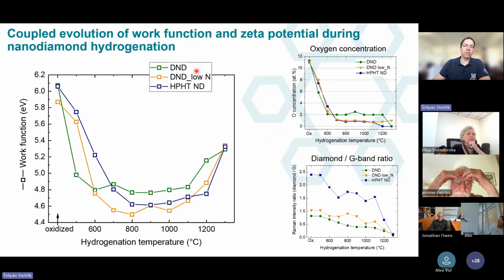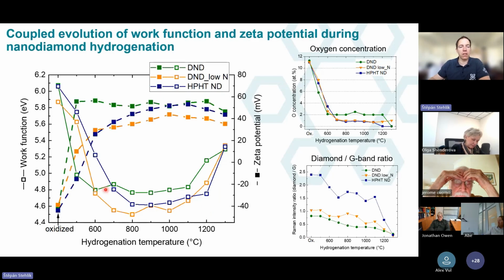But both these low nitrogen nanodiamonds need a higher temperature to achieve the full hydrogenation, and the full hydrogenation is achieved at about 700 or 800 degrees C. Okay, and let's complement it with the zeta potential, and that's the result. So when we start with the DNDs, just 500 is enough to have this very high zeta potential, and then the zeta potential is kind of stable and decreases only at this highest temperature when the graphitization is really strong.